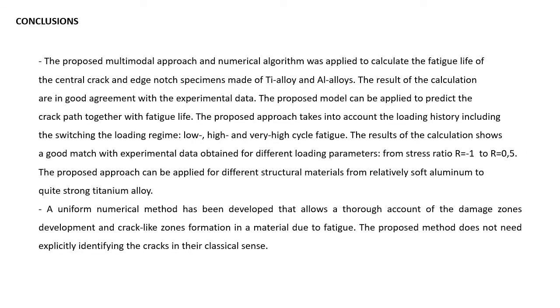Finally, the following conclusions can be stated. The proposed multimodal approach and numerical algorithm were applied to calculate the fatigue life of central crack and edge-notch specimens made from titanium and aluminum alloys. The results of calculation are in good agreement with the experimental data. The proposed model can be applied to predict the crack path together with the fatigue life.